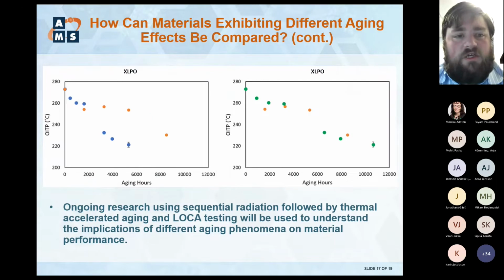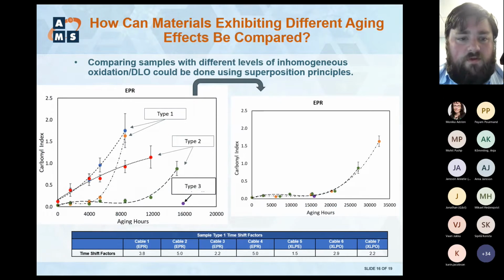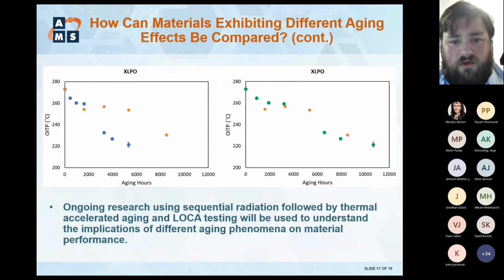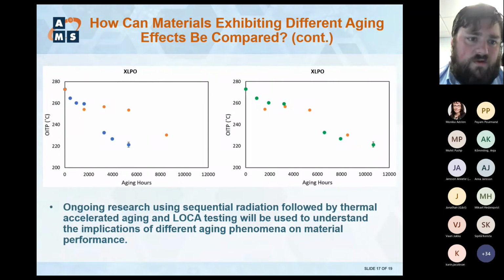This shows the application of that for oxidation induction temperature measurements. So the blue is the type 1 data, the orange is the type 2. And then using one of the shift factors we came up with doing this method, we're able to apply that, and you can see it superimposes over each other. So we're able to account for the DLO delay using this superposition approach. We're still going through these types of things.